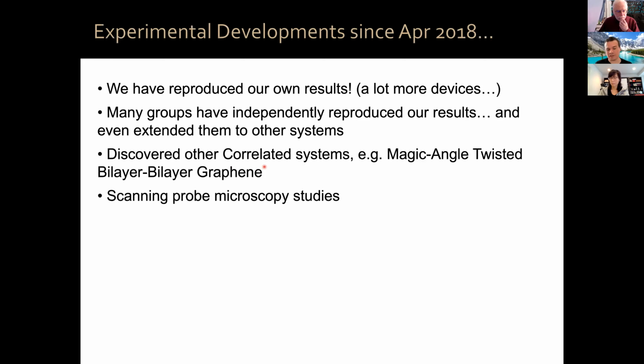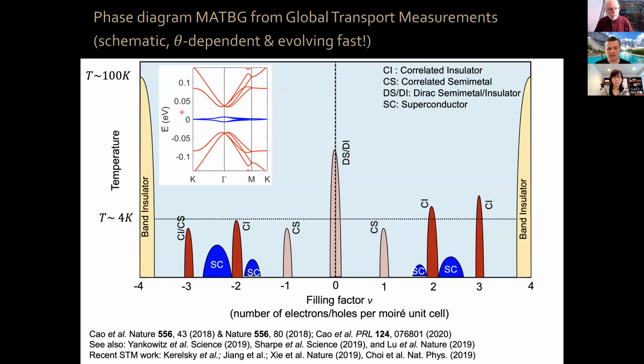Now, the other thing that has happened is that we start to have various scanning probe microscopy studies of the system, so we can look more microscopically at what is indeed going on with these Moiré systems. And this has produced very interesting data. The phase diagram that we had until these scanning probe microscopy studies arrived was entirely from global transport measurements, such as the ones that we do in my group. And just to remind you, this is temperature versus filling factor, the charge density, or the doping diagram if you want.